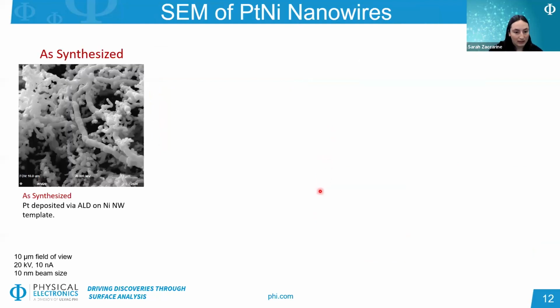So now we're going to go through and show some data for this full platinum nickel nanowire sample set, starting with this as synthesized material. So this again was using atomic layer deposition, or ALD, to deposit thin layers of platinum onto the nickel nanowires. So after the synthesis, this is one example of the wires we looked at. Like you saw in some of that smaller field of view image, we have a wide variety of diameters and lengths of these nanowires, but generally they are pretty intact. They're pretty smooth looking. We have long lengths of wires, so they seem to have this more intact morphology.